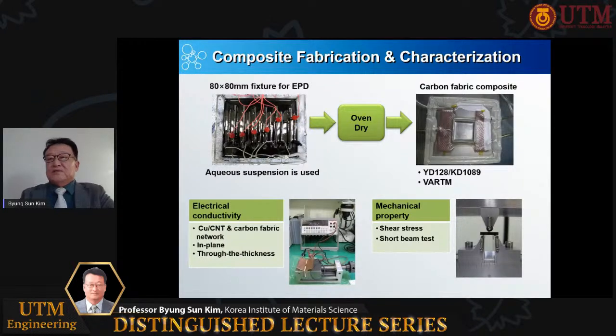In nanocomposite fabrication and characterization, 6 plies of carbon fabrics are EPD processed at the same time. Aqueous solution is used in the process. The processed carbon fabrics are dried and vacuum-assisted resin transfer molding processed to produce test specimens. The electrical conductivity tests are carried out for the copper CNT and carbon fabric network in plane and through the thickness of the nanocomposites. Mechanical tests are performed for shear stress and short beam properties of the nanocomposites.